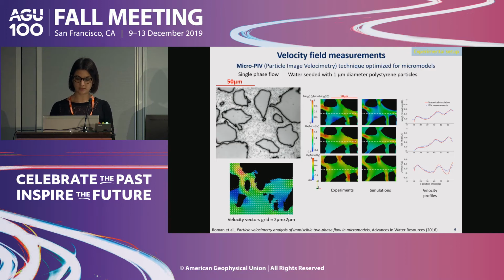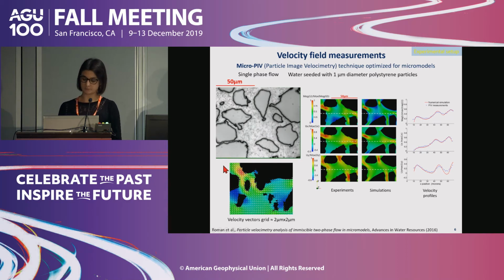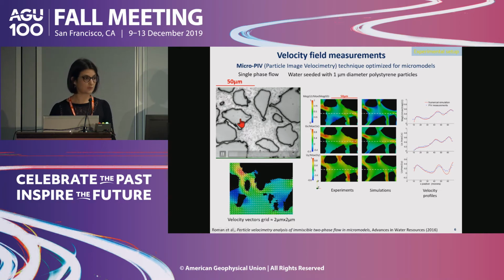We also use a technique called PIV, particle image velocimetry, that allows us to measure the velocity fields in situ. The principle of this technique is to seed the fluid, the aqueous phase, with microparticles that will follow the flow. And then from these images, we can measure the velocity field in situ. This is the velocity field that we obtain from experiments, which we compared with simulation for a single-phase case. These are the velocity profiles for both experiment and simulation. We compared them to be sure that experimentally we were measuring the velocity field accurately, and we are able to obtain velocity fields with one velocity vector every 2 microns.